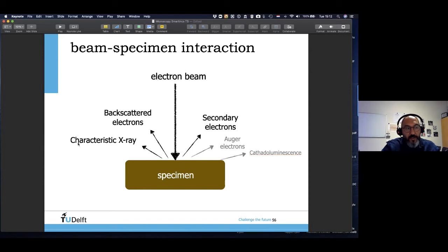And there's one more thing, the characteristic X-ray. When our electrons come and hit a specific atom, let's say a silicon atom, let's say a calcium atom, you are generating an X-ray that is characteristic in energy and wavelength to that particular element. You can imagine that if your detector is hearing that particular X-ray multiple times, it says, oh, I'm hearing a lot of signal from calcium. Let me plot them on a spectrum, and then I will get a calcium peak in my microanalysis result. It can be EDS or WDS, but again, I am not able to talk more about the X-ray part. We just put it aside and emphasize that it's important.